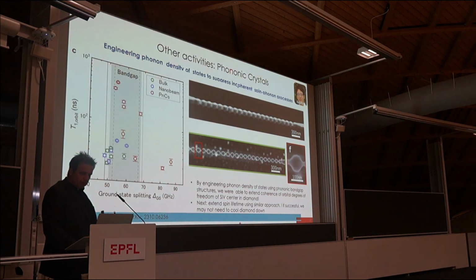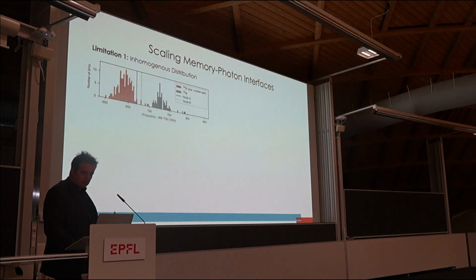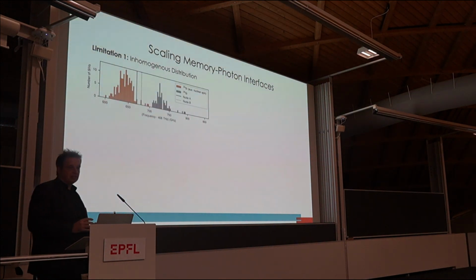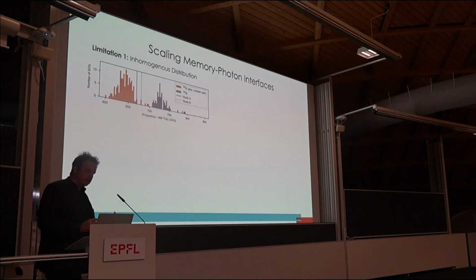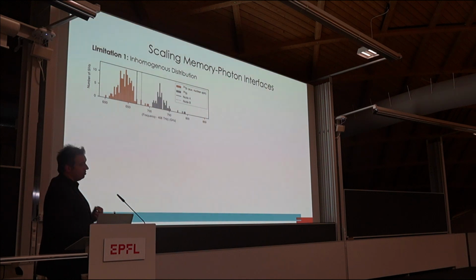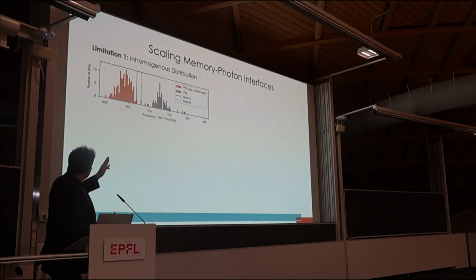So in this departure into phononics, I just want to go back to our color center, silicon vacancy color center, and photonics, and tell you a few problems with that. Right? They were already mentioned up front. One of the problems is inhomogeneous broadening, which means because each of these silicon vacancy color centers sits in a different part of the diamond, they have different strain environments. Therefore, they are actually not all emitting the same wavelength. And you can see some kind of crazy distribution. This is frequency in gigahertz.